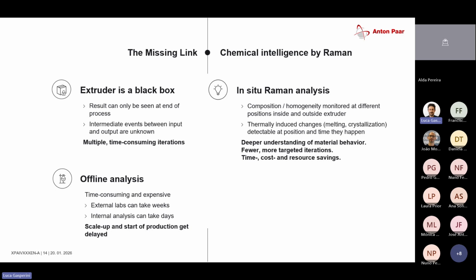Typically we get the individual components, then check the final components to see if there's actually a difference on a Raman, and then we include it into the process if we know that the temperature range and the pressure are not too high for the probe. We already know what happened because we characterize with the FTIR. We see, for example, the carboxylic acids decreasing and the ester part getting higher. It's perfect. We see it with the other analysis tools, but if we don't have to take the sample from the area with a person into the lab to analyze several parameters, and instead have online real-time measurement, it will be a huge decrease in the process time.